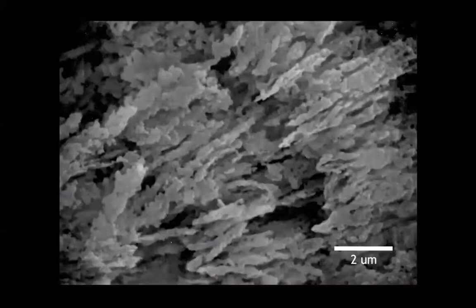So here's the proof of that, a scanning electron microscope image of these chalcedony fibers. This is an agate that I etched with hydrofluoric acid, following a recipe that Clifford Frondel, who was a mineralogist at Harvard in the 1940s through 80s, suggested. He was the one who suggested you could bring out the textures by etching with hydrofluoric acid. And so when we do that, we see the fibrosity really clearly. There are fibers radiating from the lower left towards the upper right of this micrograph.